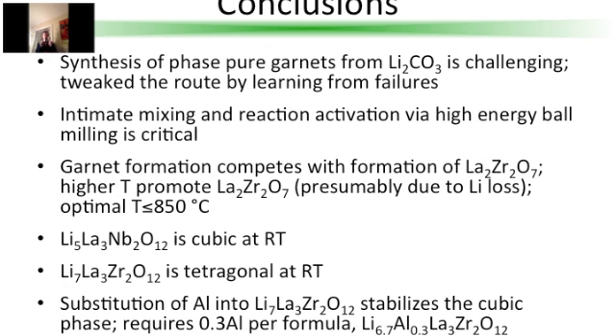Also, I found that when forming these samples, numerous reactions compete with each other. For instance, the lanthanum zirconate oxide phase competes with the formation of the lithium lanthanum zirconate phase. And what we found was that heating at higher temperatures promotes the formation of other phases. So the optimal temperatures are below 850 degrees Celsius.